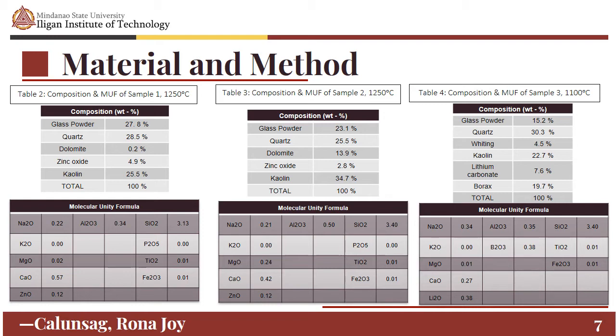And for the table 4, it is the composition for sample number 3 fired with 1100 degrees Celsius. For the glass powder, it has 15.2%, the quartz has 30.3%, the whiting has 4.5%, the kaolin has 22.7%, the lithium carbonate has 7.6%, and the borax has 19.7%, a total of 100%.